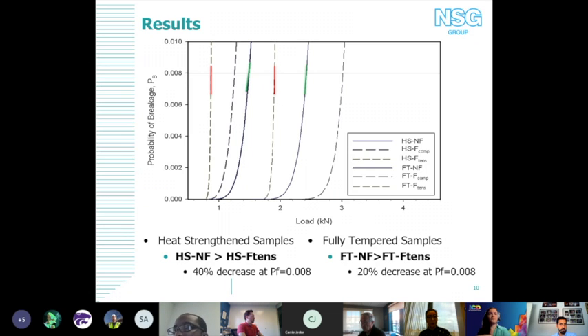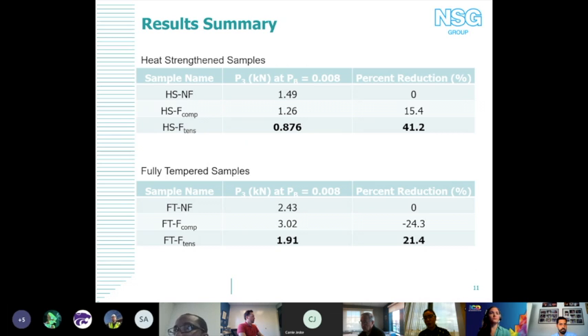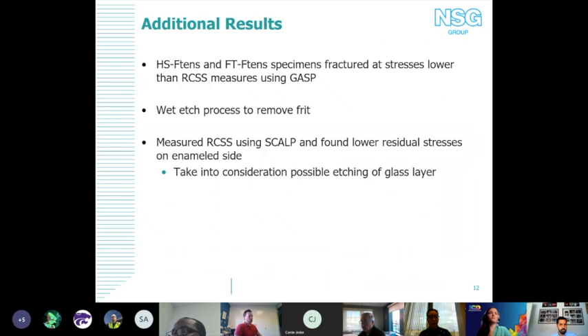Next slide. This is just a quick layout of what those percent reductions look like. We can move forward. Whenever we realized that the glass was fracturing at stresses lower than the measured RCSS, we used a wet etch process to remove the frit and try to measure what those residual compressive surface stresses were, and we found them to be significantly lower than what is actually defined as heat strengthened or fully tempered by ASTM.